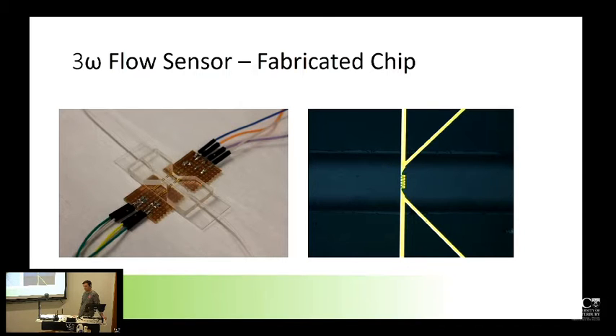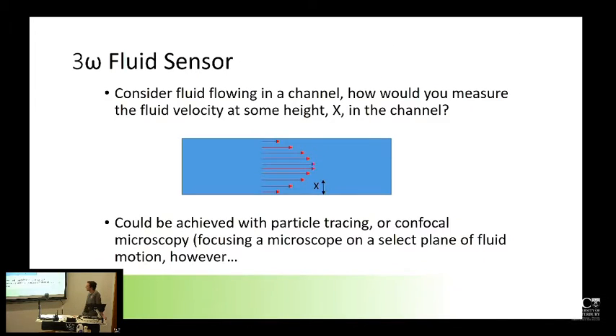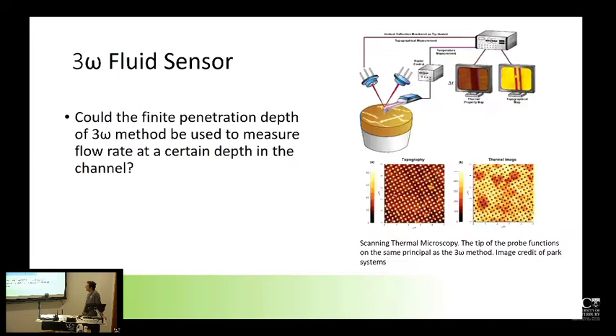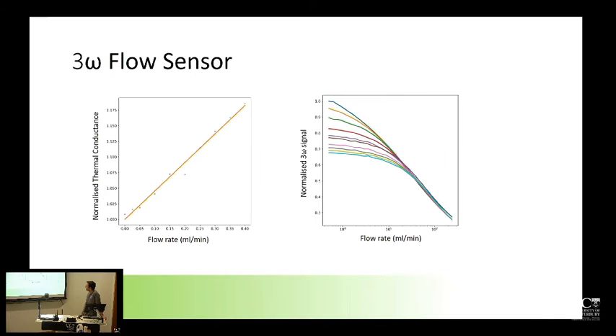And you need to know the thermal conductivity of the liquid to a degree. Yeah. Well, technically speaking, if I took the slope of this no flow condition, I can actually just measure the thermal conductivity as long as I know that the fluid is perfectly stationary. I can take this as the control case, and then it's just the difference between the control case and that, given all things staying the same after that.